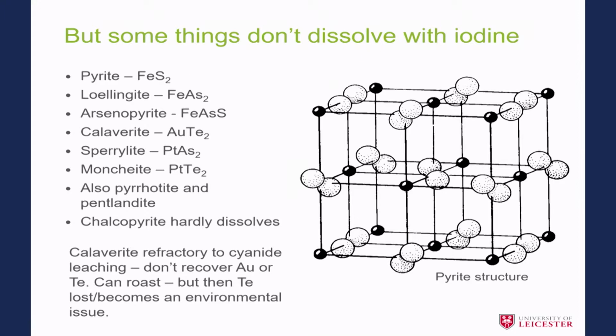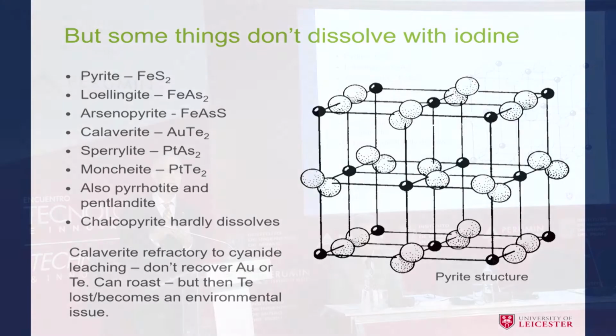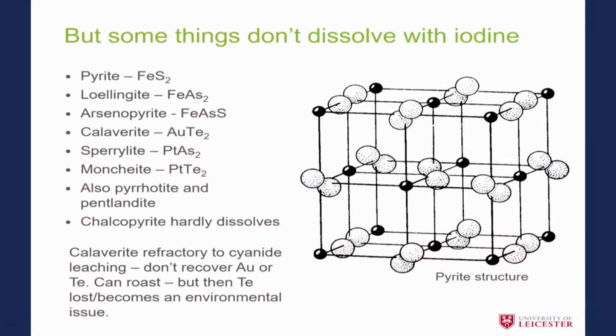Okay, so all I've talked about so far is using iodine as an oxidizing agent. But a lot of minerals don't dissolve. Most notably pyrite doesn't dissolve, but also our iron arsenic sulfides, lollingite and arsenopyrite. I guess you can see the similarity of these minerals. It's down to the structure. They have disulfide or diarsenide bonds. They don't dissolve. Now, pyrite, in many cases, we wouldn't want to dissolve. We just want to leave it because it is gangue. But we'd certainly want to recover the calaverite, the gold, and the tellurium, and the platinum minerals here.